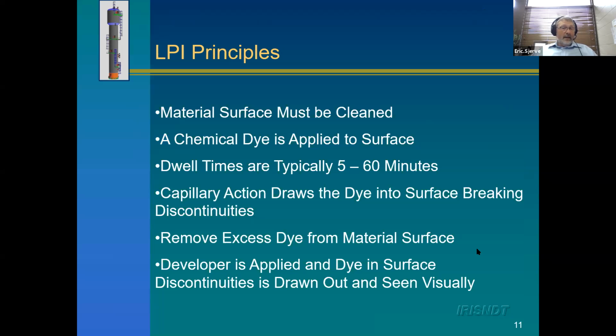So this is really a capillary action type thing where we put a liquid on the surface that has a low viscosity. So we clean the surface really well. We put this chemical dye on the surface. We let it sit for a while. Capillary action will draw it into any surface breaking defects. We just wipe the excess dye away from the surface, and then we use a developer to show us where the defects are. So LPI is a similar inspection to MPI in that it will only find surface breaking defects, but the physics is different. It's a capillary action inspection rather than a magnetic inspection.